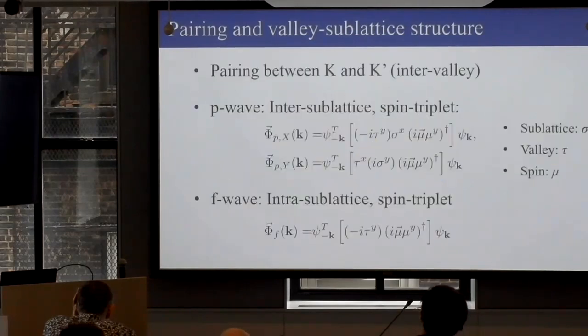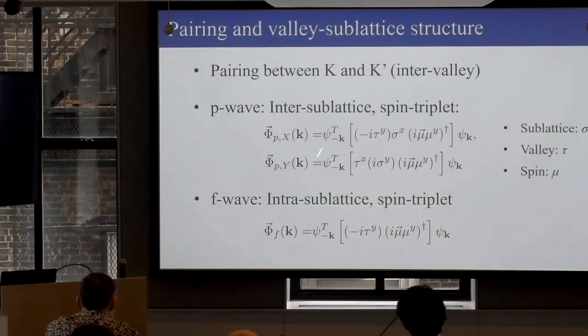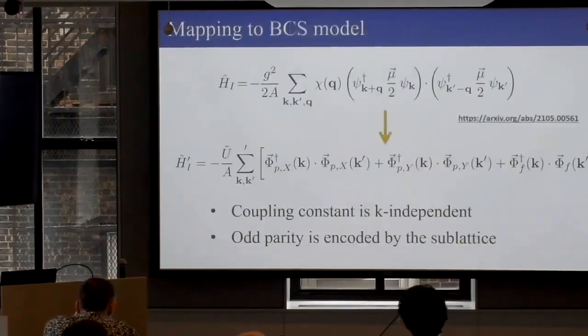And we can take into account the symmetry, including the spin fluctuation bosonic component, easily, because we've already done it with phonons. And then we can identify which channels are pairing and what the symmetries should be, P and F wave, because you can have intrasublattice, both spin triplet. It's a bit dizzying. Then we mapped into a BCS model. Here the coupling is K independent, basically a Hubbard U-type coupling.